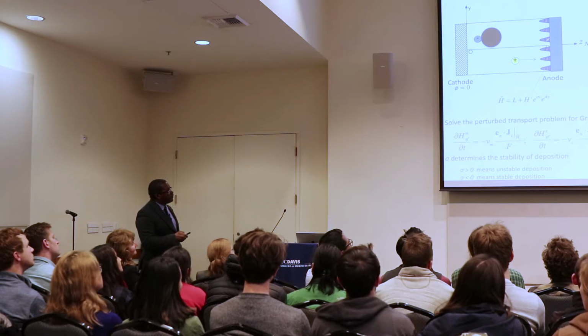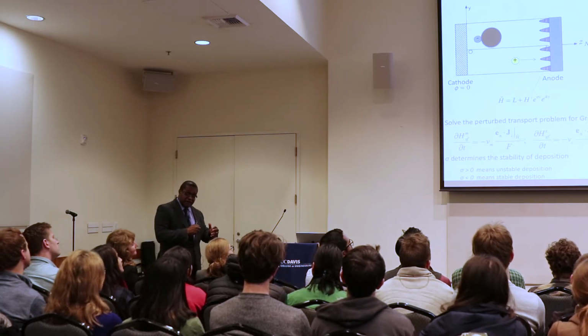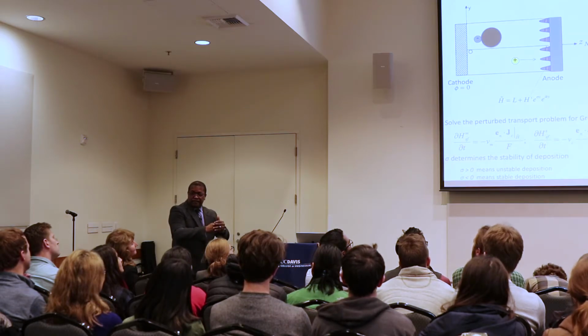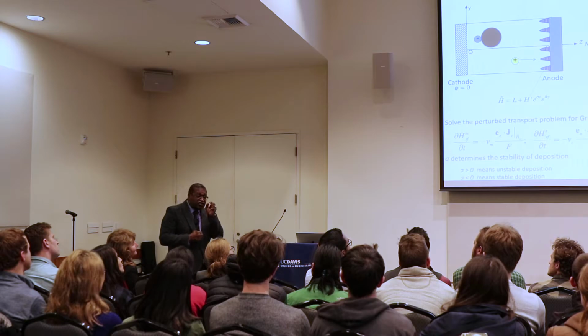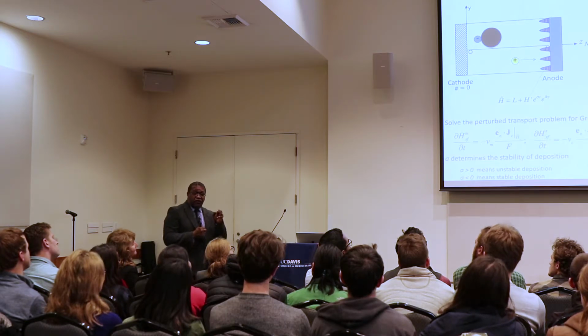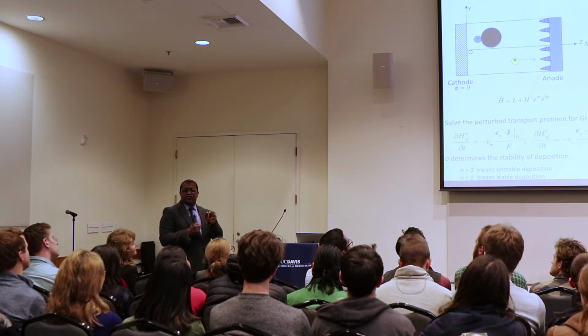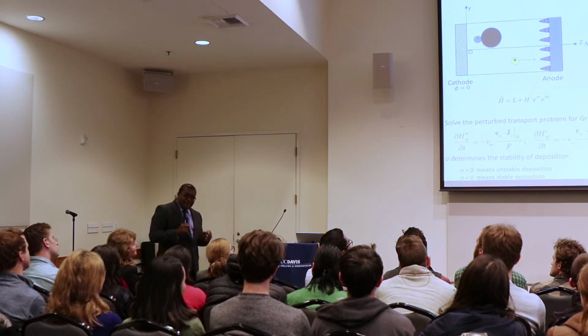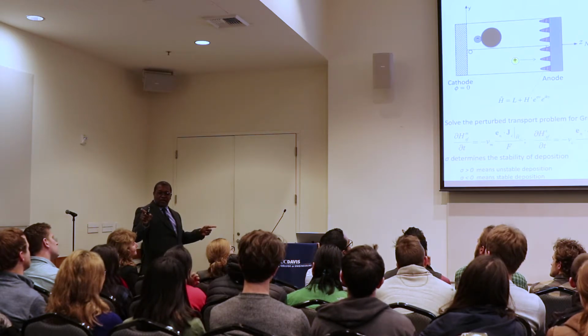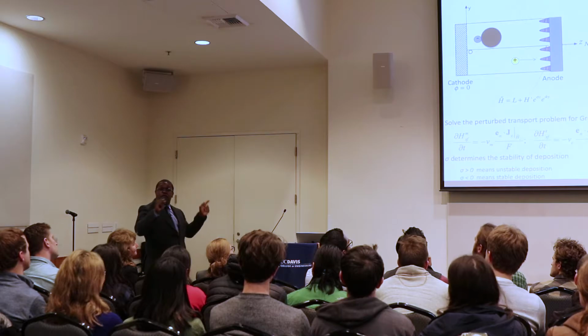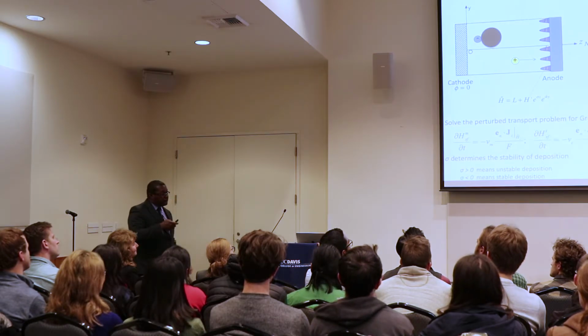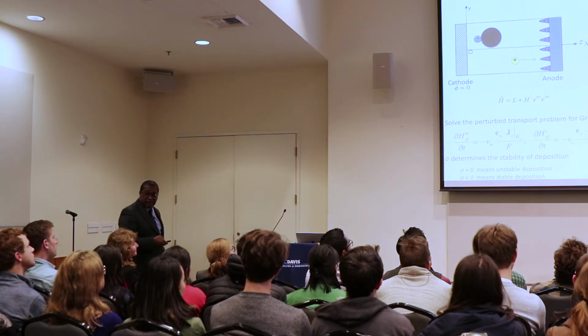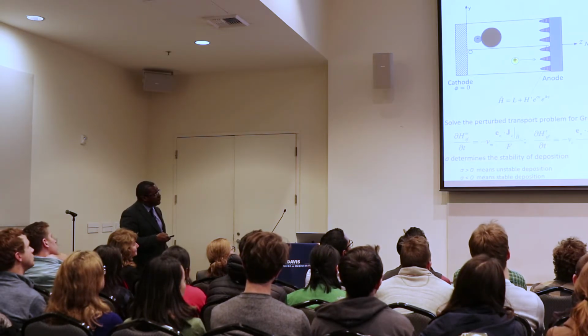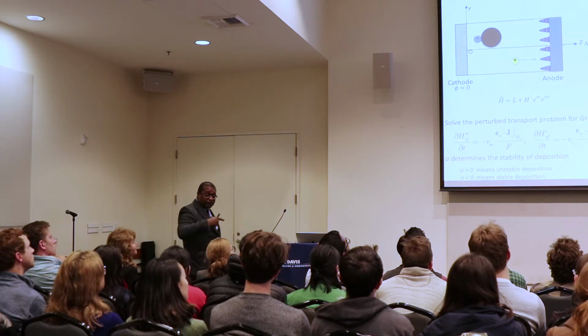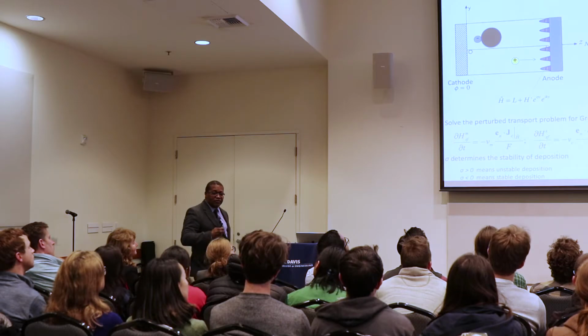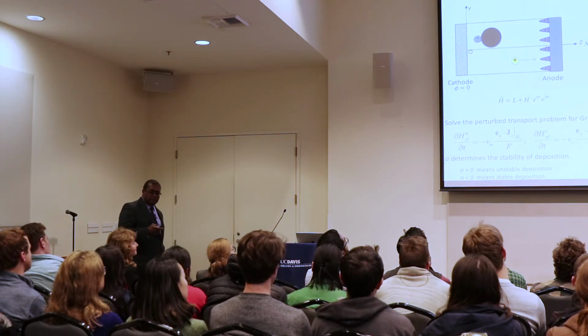And the logic of this new term was that when these bumps grow, remember the plastic separator, they press against the plastic separator. Once they press against the plastic separator, they change its volume ever so little. That change in volume, decrease in volume, causes the concentration of salt to be higher locally. Once that concentration is higher, there's a driving force for salt ions to not deposit on the bump, but away from the bump. And you can do this self-consistently by writing down expressions that relate the stress to the deformation and the pressure to the stress, and then by putting in the pressure gradients, you can solve this whole set of systems self-consistently to understand what this new hypothetical mechanism might do for you.